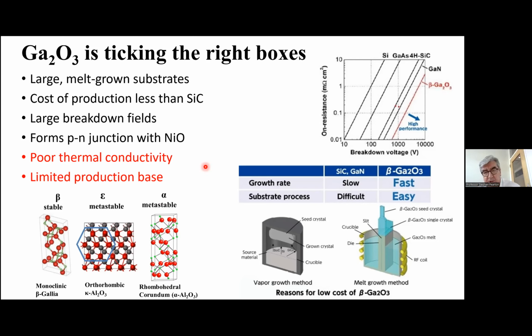Now, why do we say that these electronics are needed? If you just go to the kind of classical plot of on resistance versus breakdown voltage for different technologies, and you look at, say, 1,000 volt breakdown. So the on resistance of a silicon device would be very high, less for gallium arsenide, less for silicon carbide, less for gallium nitride, less for gallium oxide. So when you switch current in that material, you have less resistive losses if you use an ultra-wide bandgap material. And that's really the basis of their utility. Now, just the device itself isn't the only factor you take into consideration, but just one-to-one comparison, it's better to use an ultra-wide bandgap material, provided you can make the cost of manufacture reasonable for commercialization.